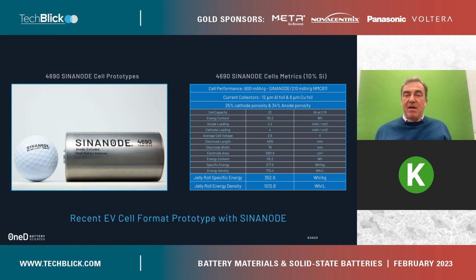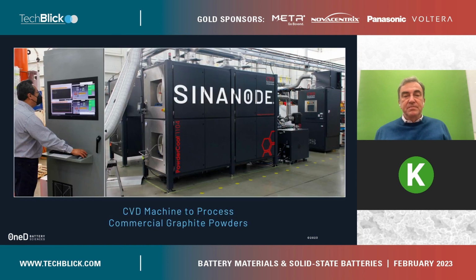What's important is that 600 milliamp hours per gram is all active material. It's either silicon or graphite. It doesn't include the traditional amorphous carbon or the excess binder. So you can make cells with less than, let's say, 5% of total inactive material in the anode electrodes, and you can pair that with NMC 811 or NCA, etc. And what you end up with is cells that have a respectable 32 amp hour in that format, that are tabless and achieve at a jelly roll about 350 watt hours per kilogram, and on a liter basis about 1,000 watt hours per liter. Now, this is not ready to go into EV cell production. This is just a sample that we provide our customers as a proof of concept. An actual EV cell takes more work and more time, and we do that with each of the customers.